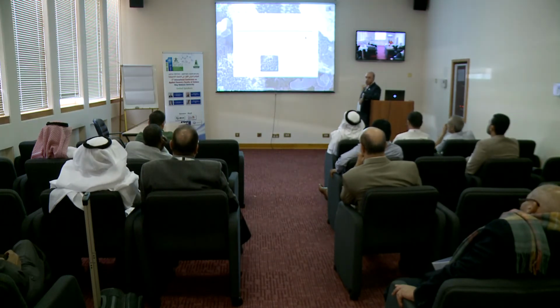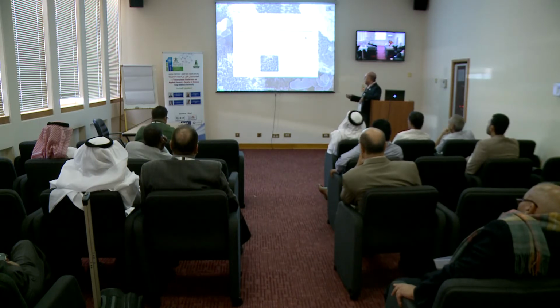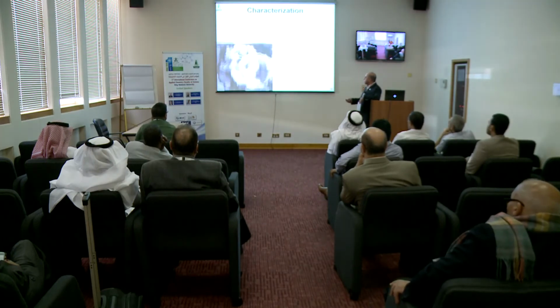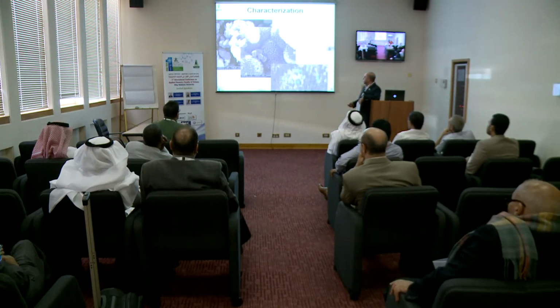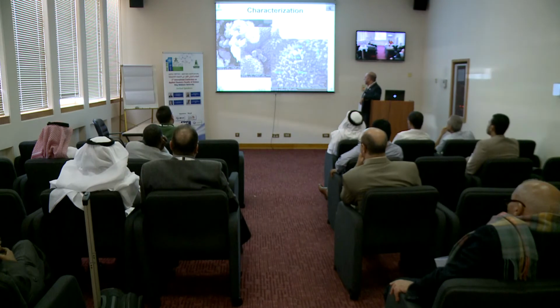Today I'm going to talk about four of my recent publications with my group. The first one is the synthesis and characterization of a novel manganese oxide. This novel manganese oxide, we prepared it in the lab by accident, and we found it to have very, very good properties. It is actually in the form of nanocorals, as you can see here. This is the scanning electron microscope image of the manganese dioxide nanocorals that we found.